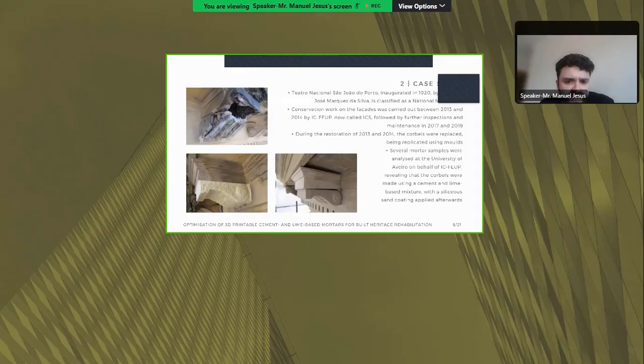During the restoration, these elements shown here in the pictures are corbels that were replaced and were replicated using some molds. Several mortar samples were analyzed at the University of Aveiro and revealed that the corbels were made using a cement and lime-based mortar with a siliceous sand coating applied.